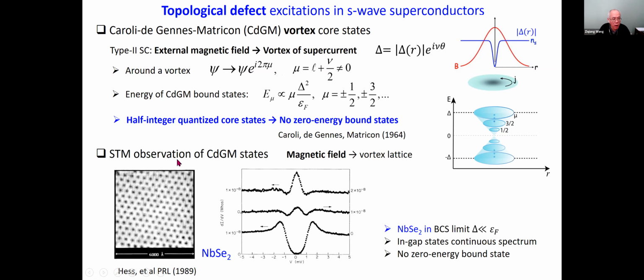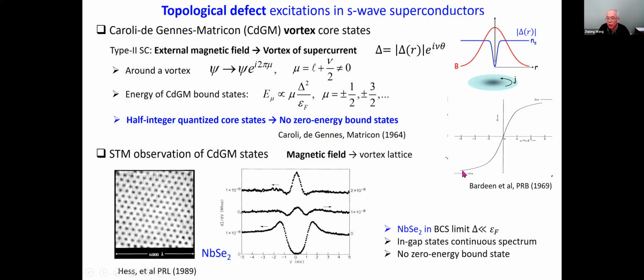And these are observed, of course, in niobium diselenide, where this is a curve away from the vortex. And as you go to the center of the vortex, you see these vortex core states. It's important to know that niobium diselenide is in the BCS limit. That is, the gap is much less than the Fermi energy. So these in-gap states are actually continuous. And this is a very nice calculation done by Bardeen, and it's a very interesting paper to read, where he calculated these states and showed that they are continuous states, interpolating between one gap and the other gap. That's why you see this.